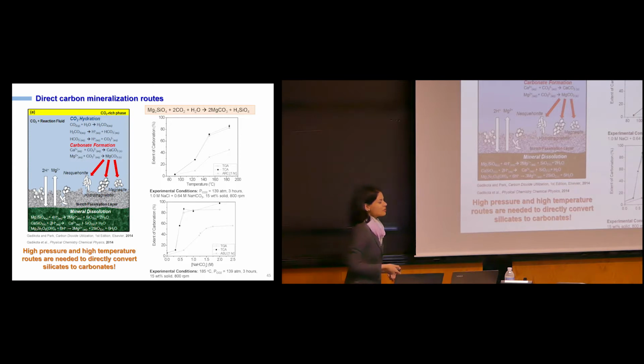So what is it that we're doing on that front? I did a lot of work looking at multiphase reaction environments where you can have CO2 in the supercritical phase, how that interacts with water, and how that might interact with a co-solid that's present. So basically you get CO2 dissolution in water, you get speciation, you can dissolve the mineral at the same time, and you can form calcium and magnesium carbonates. But if you look closely at the temperatures at which this is happening, this is all happening at temperatures above 150 degrees centigrade and CO2 partial pressures of above 139 atmospheres, right?